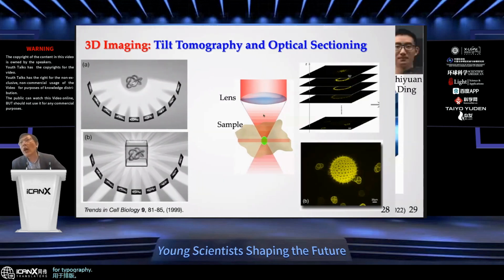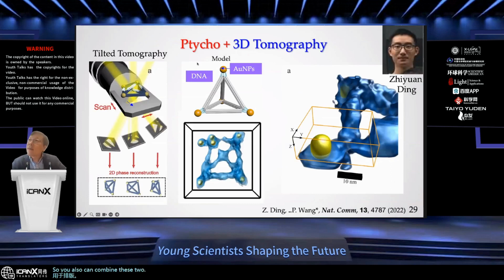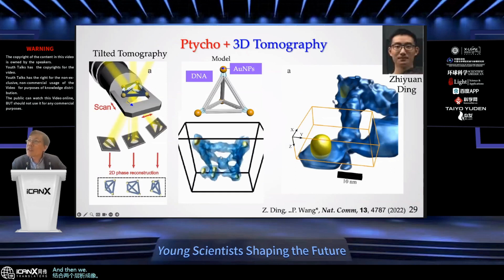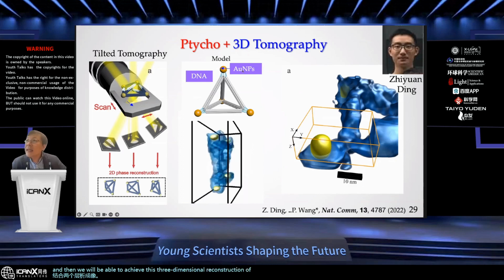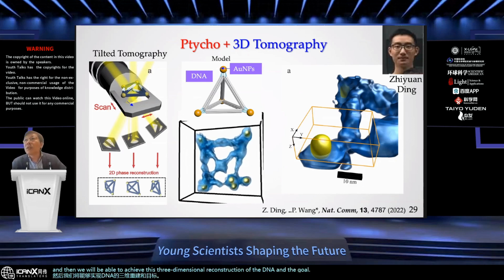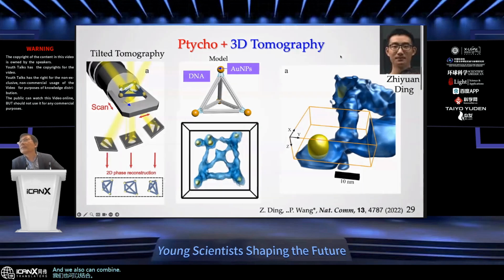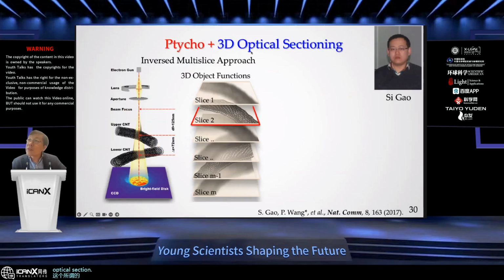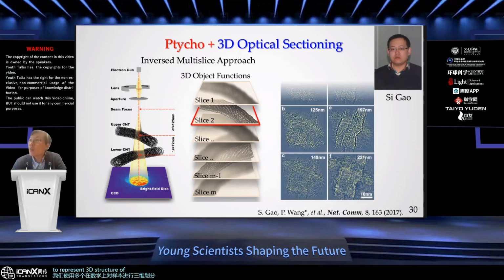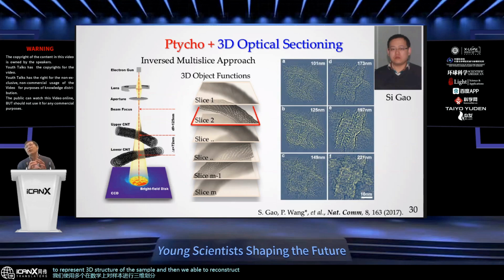For ptychography, you also can combine these two techniques, and by combining with tilt tomography, we will be able to achieve this three-dimensional reconstruction of the DNA and the gold particle. And we also can combine with the so-called optical sectioning, the three-dimensional optical sectioning. In this case, we divide the sample mathematically in three dimensions using multiple slices to represent the 3D structure of the sample,